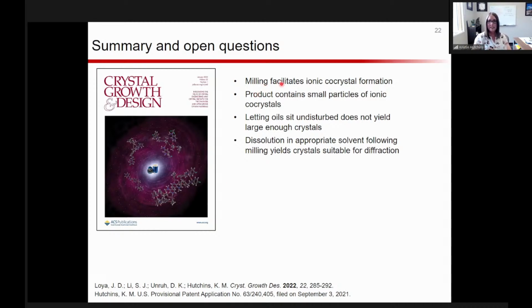And so in this study, we again showed that milling facilitates the ionic co-crystal formation. And we think that even though it's an oil sort of material, that product must contain particles of the co-crystals, again, as evidenced by spectroscopy and by powder X-ray diffraction. We did decide to let those oils sit undisturbed for several months, 8 to a period of 11 or 12 months, to just see if they would spontaneously grow large enough crystals that we could pull out for single crystal diffraction. But unfortunately, they did not. We could tell by optical imaging that there was, again, these really tiny particles, but nothing that we could pull out and do single crystal diffraction on. And that dissolution following milling gave us the crystals that were suitable for diffraction.